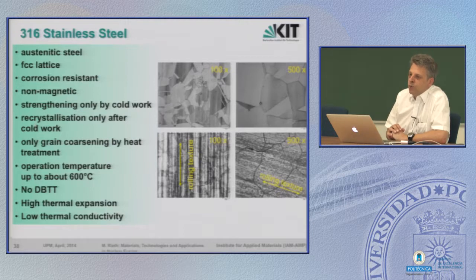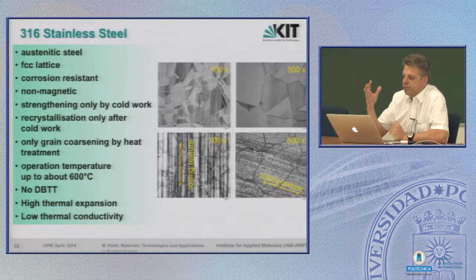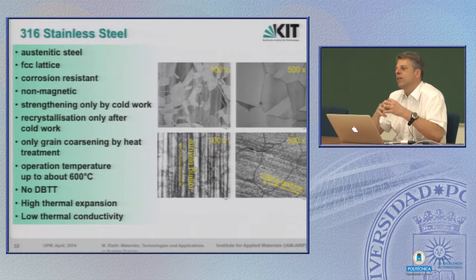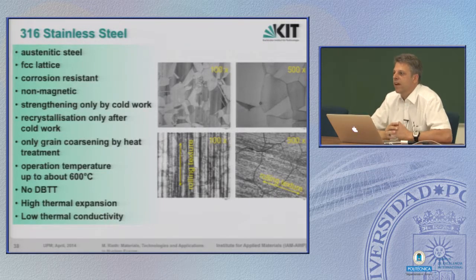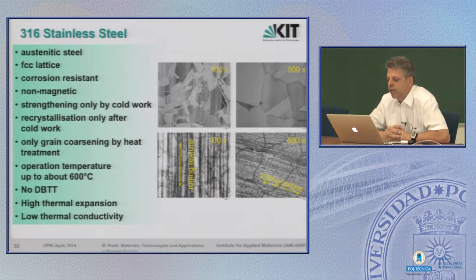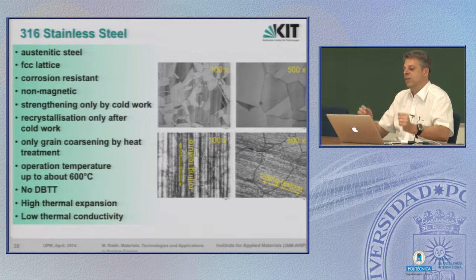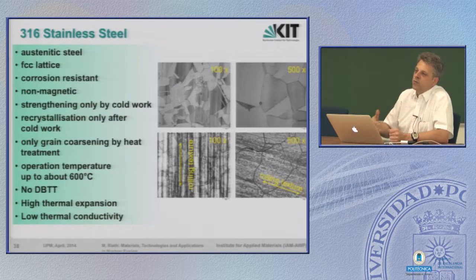recrystallized after cold work. This means if you have a component and by an accident or whatever, grain growth happened and the grains are too coarse for the further application specification for this component, well, you can throw it away, because cold working a component means destroying it, so you have no measure to restore or restructure microstructure in a real component. That's the main drawback here.